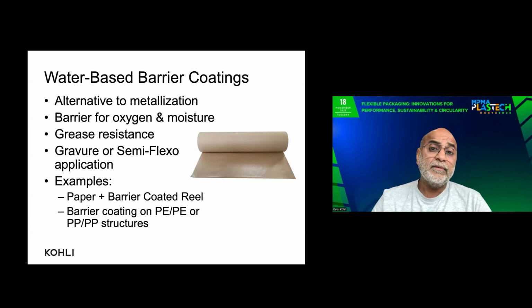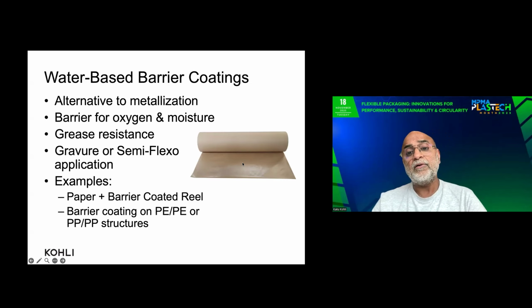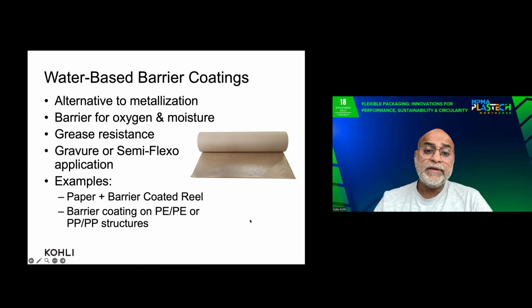Water-based barrier coatings. Basically, we are trying to get some barrier properties and find an alternative to metallization. Because even after this water-based barrier coating, the film has to have a proper barrier against oxygen, moisture, and it has to be grease resistant. So you see the reel on the right. This is a reel of paper, and we have done a water-based coating on it. This was done by using the gravure or a semi-flexo coating application. So the example of water-based barrier coatings you see here is a paper with a barrier coated reel. But we can also do barrier coatings on PE or PP structures.